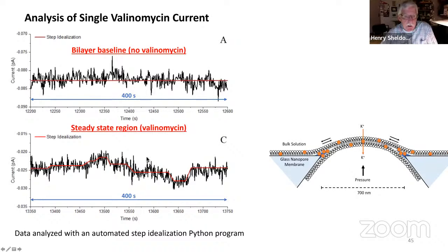And what Alex has done, she's developed a Python script that lets her go in, and it's completely automated, and determine where statistically there are steps in the current time trace. So that's what this red line is here. And it's also shown up here applied to the baseline data as well. And so when you draw the red line in, now you can imagine there's steps, but there's so much noise here. Looking at just one of these steps, it's not overly convincing that this is a molecule, valinomycin, when the current increases. This is an increase in valinomycin in the bilayer from, say, 25 molecules to 26 molecules.